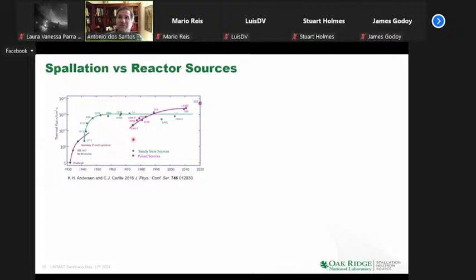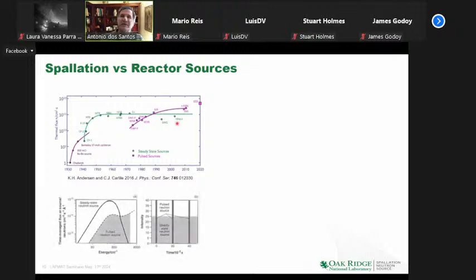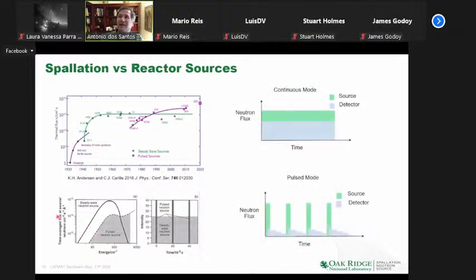Now, take this with a grain of salt, and the reason for that is that when you have a steady state reaction, the time integrated flux is much higher than those peak pulses. What you don't have is a time structure. So basically, when you have a steady source, you have a monochromator and you keep measuring all the time at that wavelength. When you have a pulsed source, you have this big sharp peak of created neutrons, and as they travel through the instrument, you start separating the different velocities as a function of time, until the next pulse comes out. So now you have a whole range of wavelengths at your disposal.